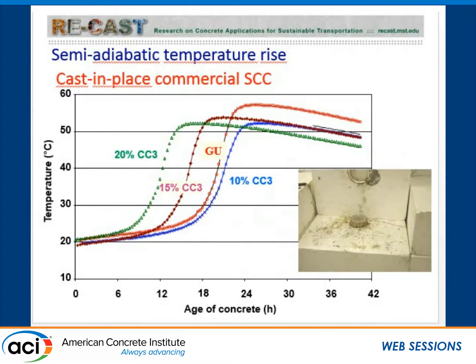We also looked at the heat of hydration, and this is semi-adiabatic using a 6x12 cylinder that is insulated in a styrofoam box, about 3 foot cube, and you are looking at the cylinder over here in the styrofoam cube, and you're looking at the semi-adiabatic heat rise, and the second one from the right is the type 1 cement or the GU. You see with the 10% CC3 you have a little bit of a shift, a little bit of a delay in terms of the dormant period, but with the 15% and the 20%, the dormant period gets shorter, so the end of the dormant period is shorter, and then initial setting and the final setting would be also faster than the type GU cement. So 15-20% is enhancing the early properties, the heat of hydration, and development of the microstructure.